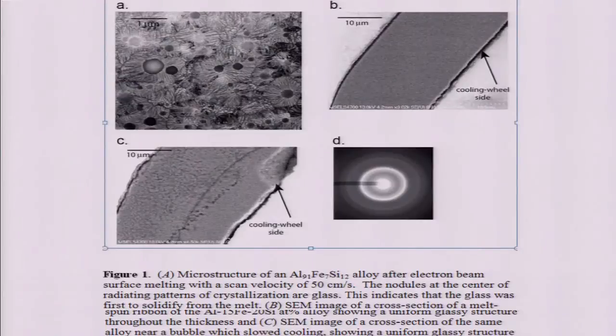And here's a picture of it. Here is primary glass, primary glass, primary glass, primary glass, and surrounding each glass particle is a eutectic of glass and aluminum. This is an aluminum iron silicon. So for metallurgists, this is no problem. We know this is the primary phase. That came first, and then other stuff crystallized. So this glass grew from the melt.